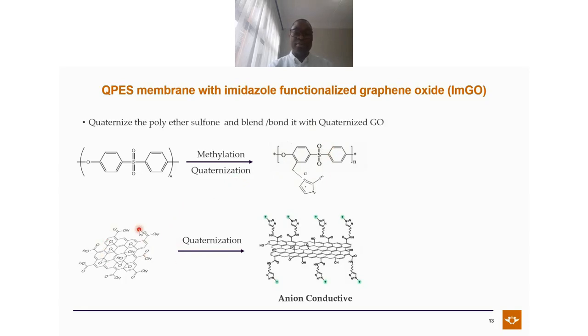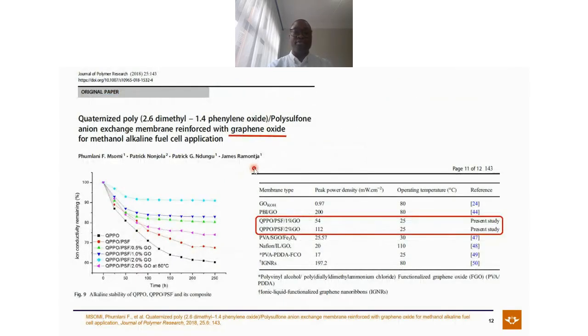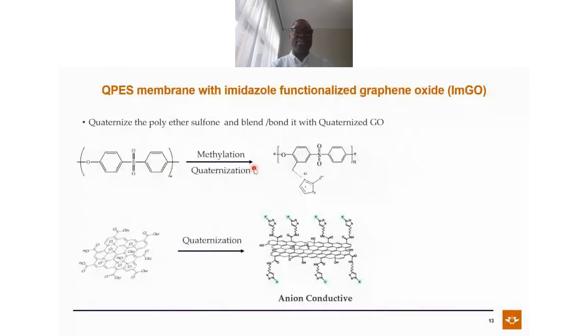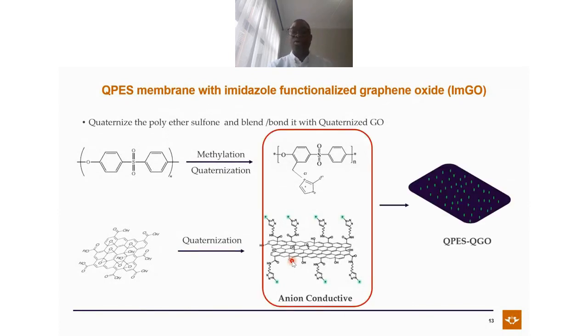Then they took graphene oxide. Remember, we said in this paper the graphene oxide was never further functionalized. It was left as graphene oxide. In this case, we took graphene oxide and functionalized it also with imidazole. So now we had a system which is quaternized in both parts. The membrane is quaternized, which means it's able to transport OH minus. The filler, which is graphene oxide, is also imidazole based, so it's able to conduct. So by looking at it, we're supposed to have high power output and also high ion conductivity. When we combined these two, we ended up calling the system quaternized PES blended with quaternized graphene oxide. Remember, these are the sites which conduct the OH minus through the membrane.